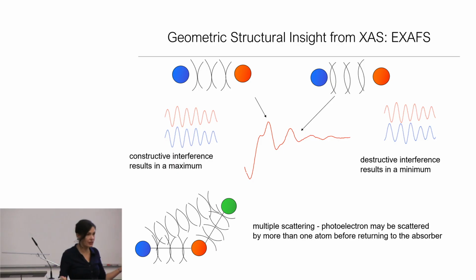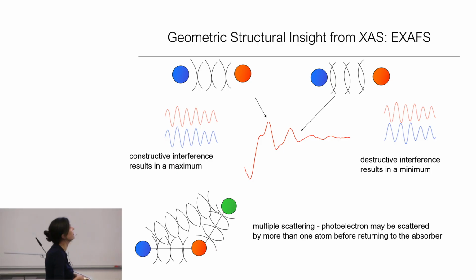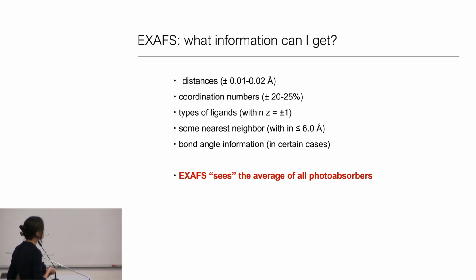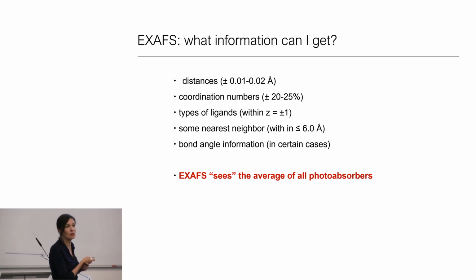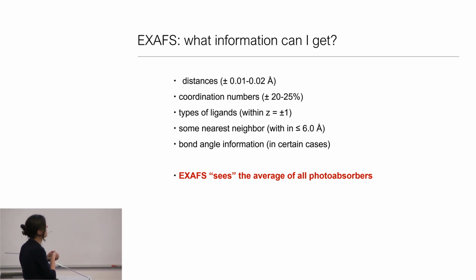Right? So there are many, many events that are happening, and we're trying to deconvolute all of that to get structural information out. And so one thing that EXAFS is quite good at is getting distances on the order of about 0.01 to 0.02 angstroms. It's not very good at coordination numbers, and this has to do with the fact that there are many correlated parameters in terms of disorder parameters, amplitude reduction factors, that all correlate with coordination number. And this is a place where you could see, hey, my edge could help me. If I thought about my pre-edge, I could reduce that error, perhaps. It tells you about types of ligands within Z plus or minus 1.